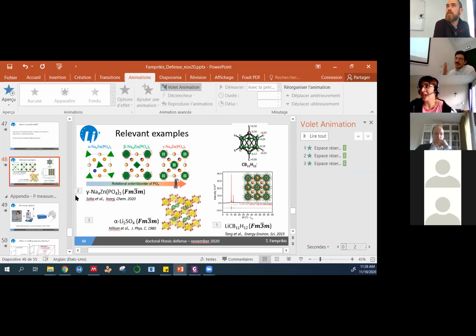Right. Well, I don't have the answer, but did you check if you have other compounds where you have a lowering in symmetry when you increase disorder or temperature? Apart from the analogy with the copolymer, in the inorganic field, did you find something? There are examples of lowering symmetry with increasing temperature, yes, but with no real distinct connection with what we see here. The lowering in symmetry is one aspect, but all the other weirdness that happens should be considered as a whole. What I've looked for specifically is any other FDDD phases with rotational disorder, and I can say that I have not found any.